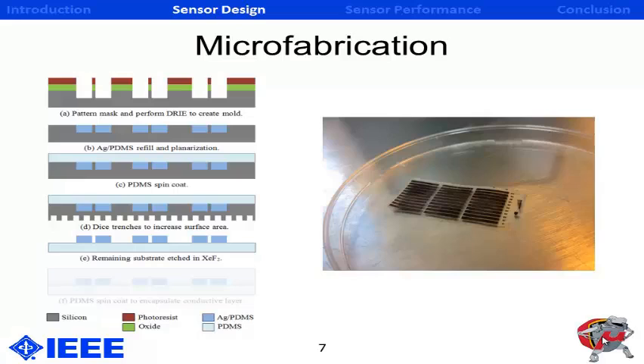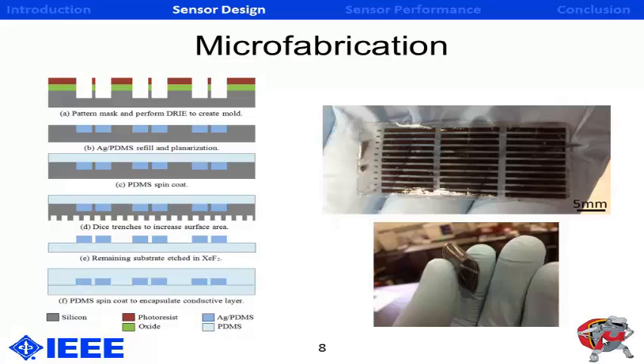Next, the mold is removed in 2 steps. The backside is first diced to increase surface area, and then it is placed in xenon difluoride to fully etch the mold. The surface area is important just to decrease the etch time in the xenon difluoride, but even after that step, it can take upwards of 16 hours to etch for an area this large. Lastly, the backside is again spin-coated to encapsulate the device, and the overall thickness is 400 microns, which is within our target, and it remains very flexible.